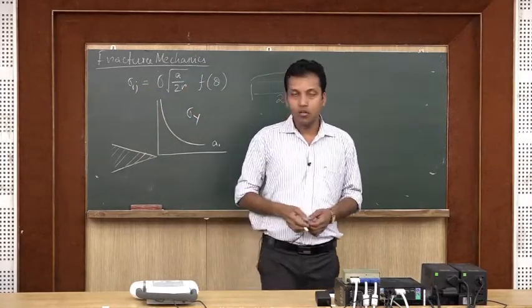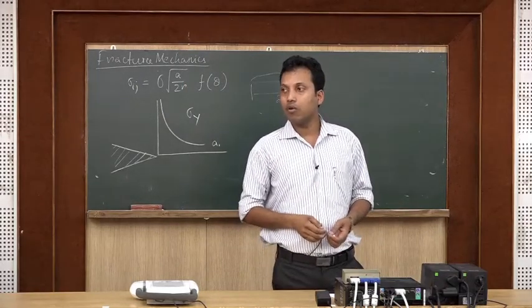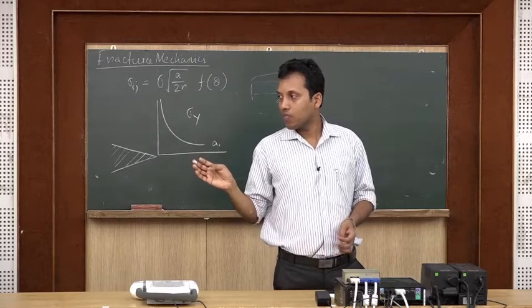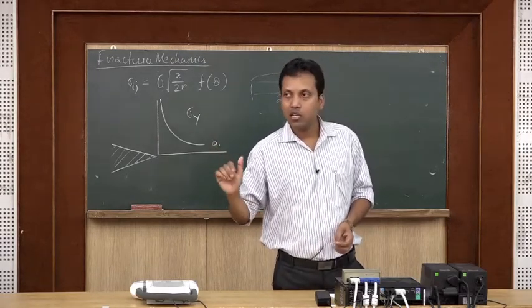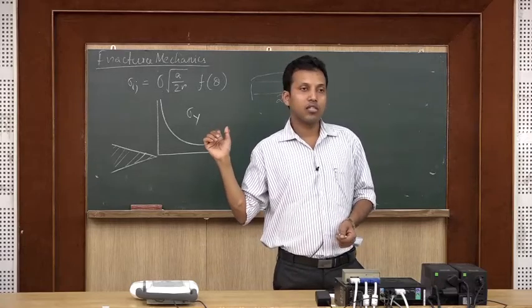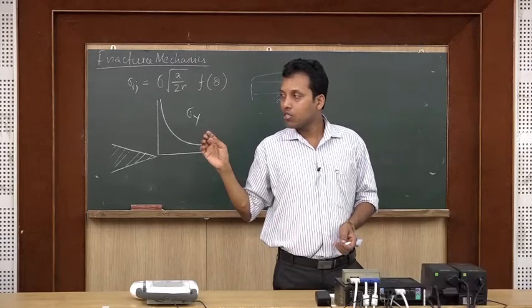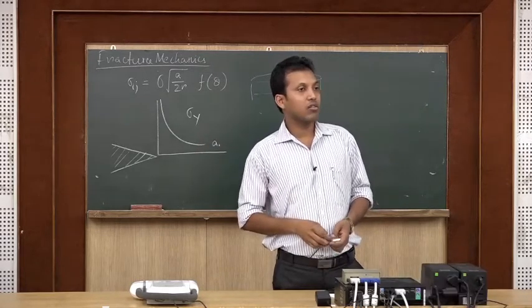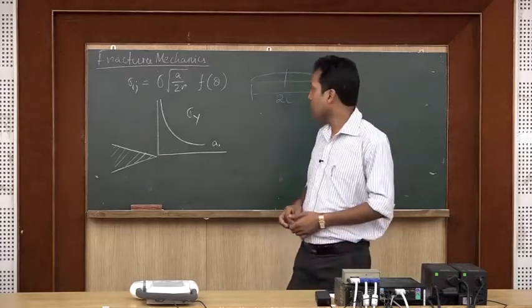Okay. So, we can write instead of sigma y here, because that may be varying, say we are writing as sigma ij. Okay. It may be sigma x, it may be sigma y for the case of plane stress, and if it is a plane strain condition, then this particular sigma x and sigma y will be having one more term which is sigma z, and sigma z equal to nu into sigma x plus sigma y. Okay. I think that you know.